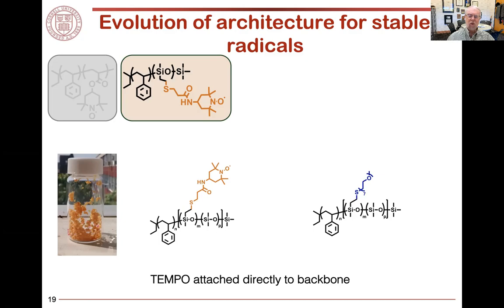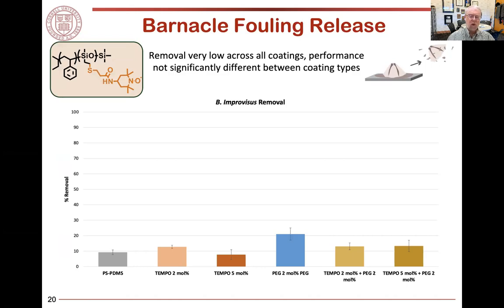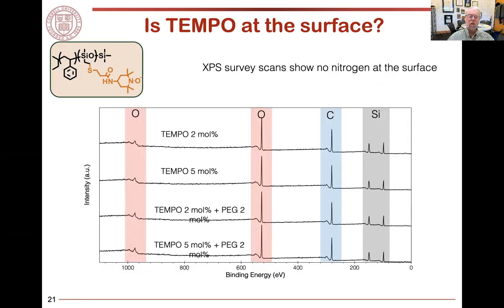And we combined it with a second amphiphilic polymer in order to produce a coating. And so what we learned there was that as we incorporated more of the TEMPO group and blended it with the PEG material, really the barnacle was quite happy to sit on the surface. And that was very perplexing because we knew that the TEMPO would be interfering with the curing of the adhesive. And what we eventually realized was that the PDMS is very, very nonpolar. We knew that. The TEMPO itself is also extremely nonpolar, although it has a number of polarizable elements in the structure. The presence of the 4 methyl groups to shield the stable radical group makes it very, very nonpolar.